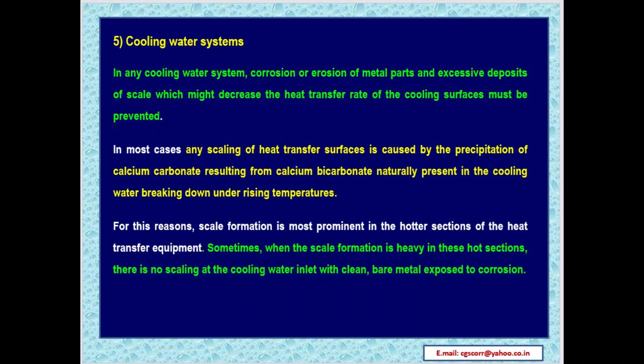And the fifth factor causing corrosion in a power plant system is cooling water systems. In any cooling water system, corrosion or erosion of metal parts and excessive deposits of scale, which might decrease the heat transfer rate of the cooling surfaces, must be prevented. In most cases, any scaling of heat transfer surfaces is caused by the precipitation of calcium carbonate resulting from calcium bicarbonate naturally present in the cooling water, breaking down under rising temperatures. For these reasons, scale formation is most prominent in the hotter sections of heat transfer equipment. Sometimes, when the scale formation is heavy in these hot sections, there is no scaling at the cooling water inlet, with clean, bare metal exposed to corrosion.